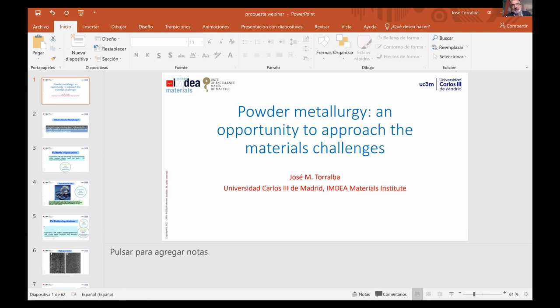And in additive manufacturing, most of the people are using the so-called Cantor alloy. If you are in this field, you will know what the Cantor alloy is. Cantor was the first person who developed one of the high entropy alloys. It's an iron, cobalt, manganese, nickel, chromium based alloy. And in that case, there is one element which is playing a really interesting role, which is aluminium. Aluminium in the Cantor alloy used to replace the manganese or even one of the other four elements.